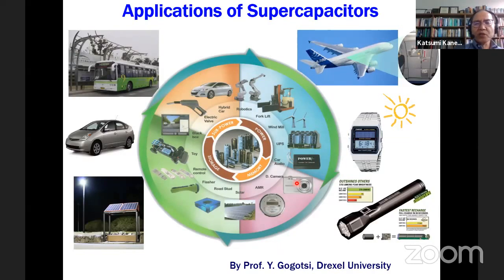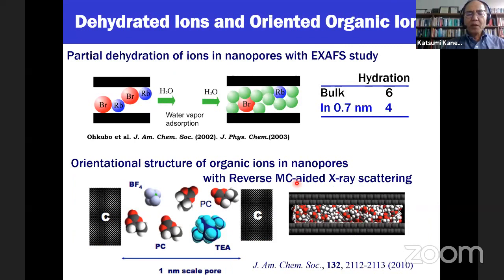So here I show how important supercapacitors are. This slide is produced by Yuri Gogotsi's group. I'm interested in the confined ions. I started work in very old times. Once we found the ions confined in small pores of activated carbons, 0.7 nanometers, the rubidium ions, the hydration numbers decrease compared with bulk. So we said partial dehydration occurs under the highly confined situation.